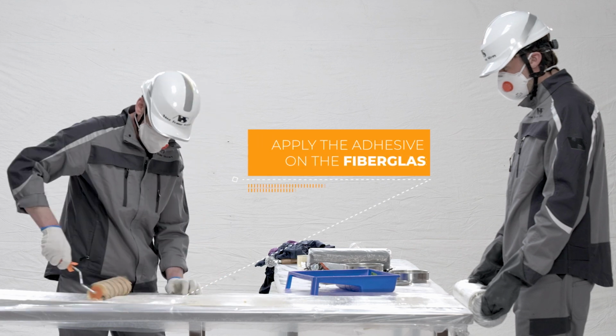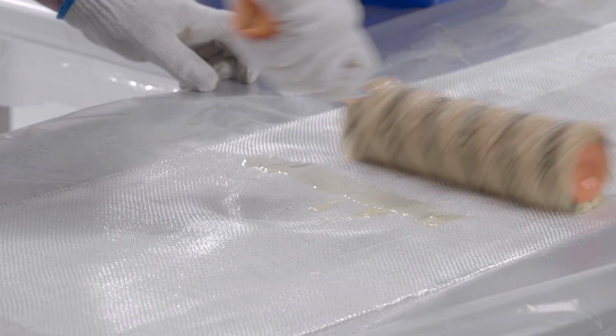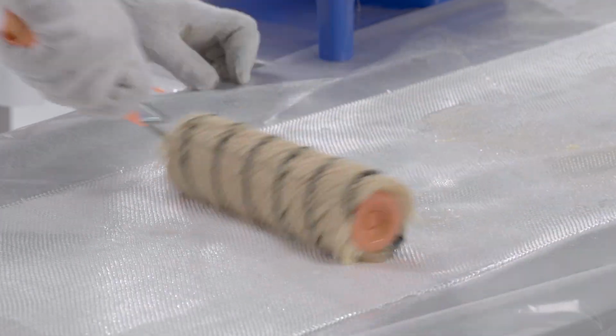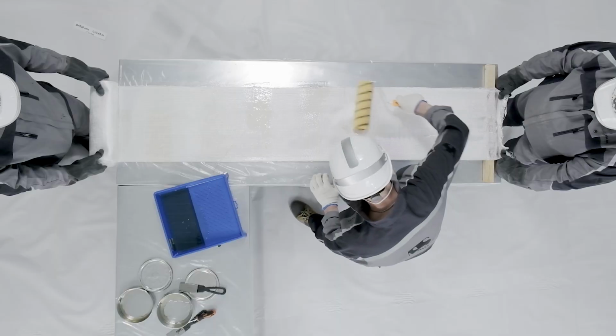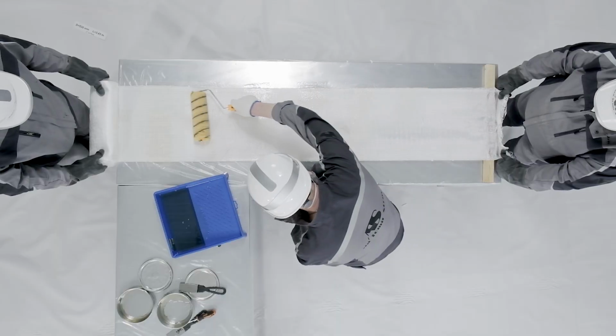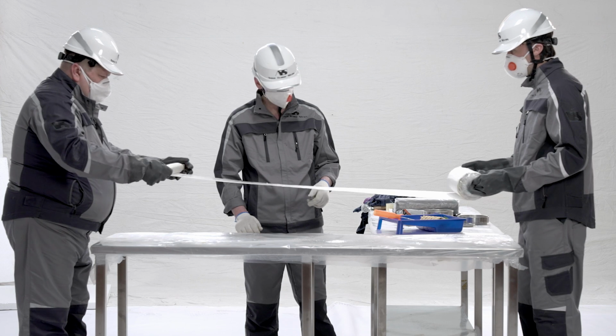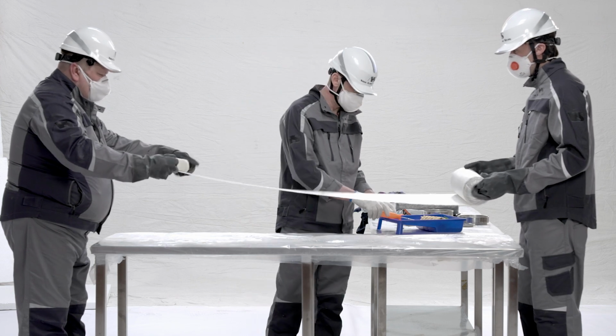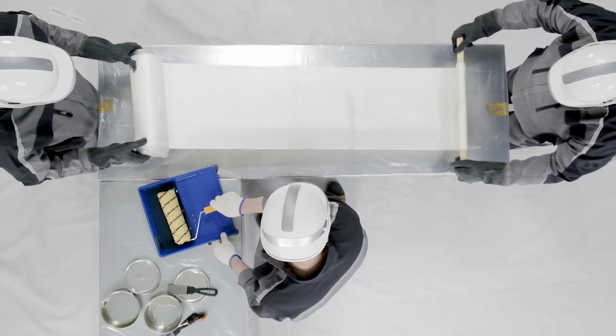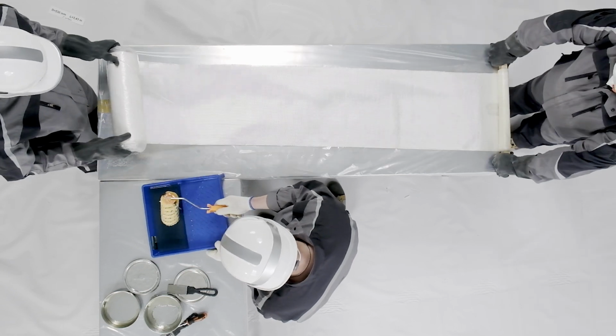Once the composite fibers are impregnated with glue, the curing process is irreversible. Therefore, it is necessary to mix kits of glue and apply it to the composite fiber after completing all the previous steps. After mixing the resin part and the curing part of the glue, the contents are poured into the paint tray.